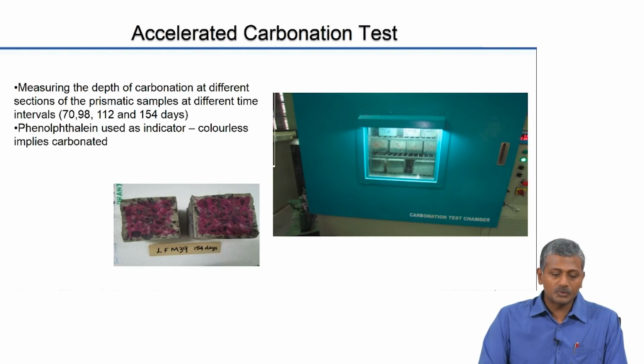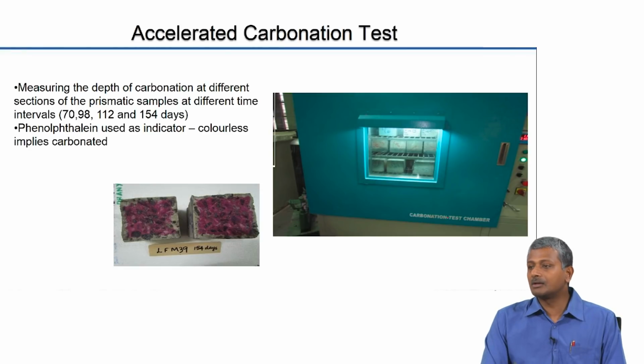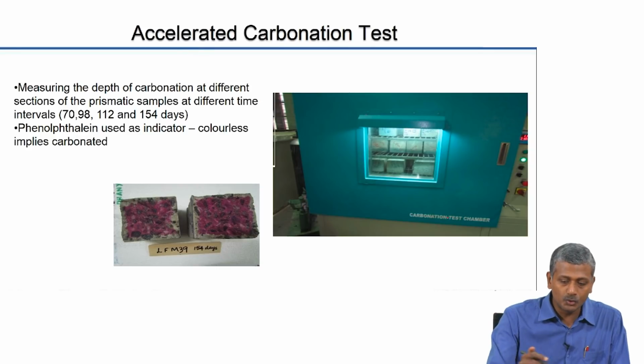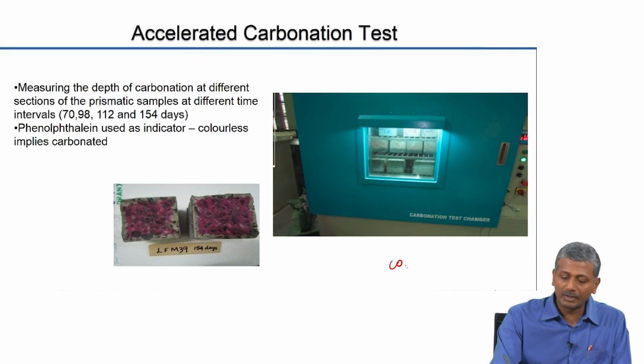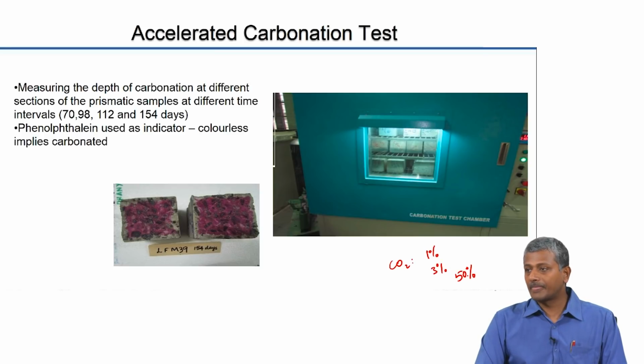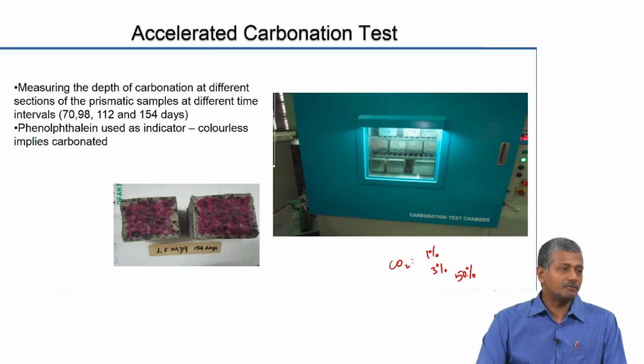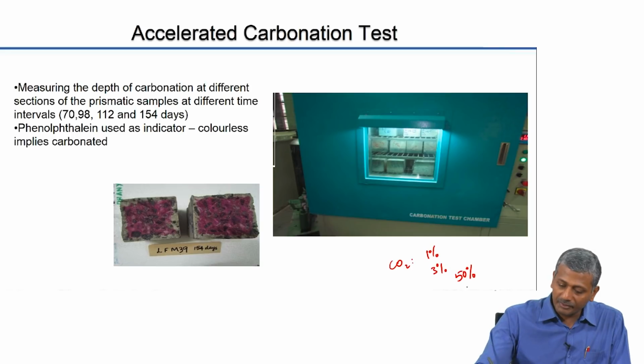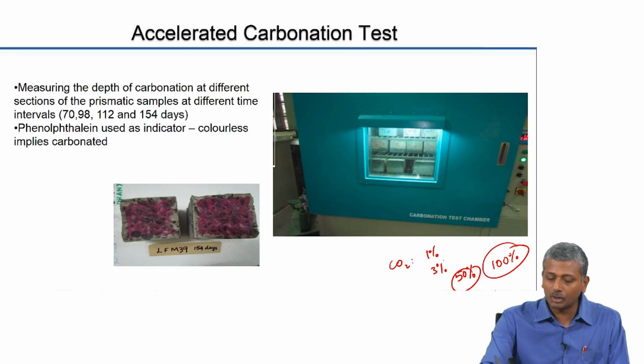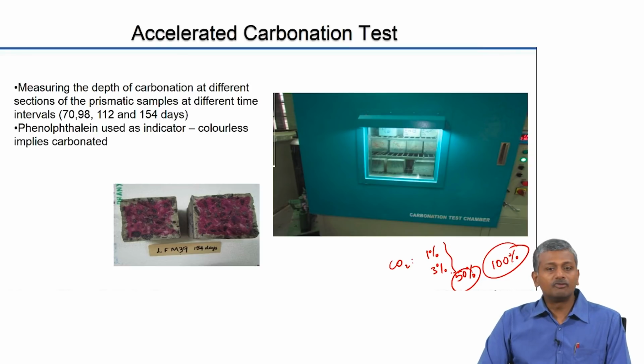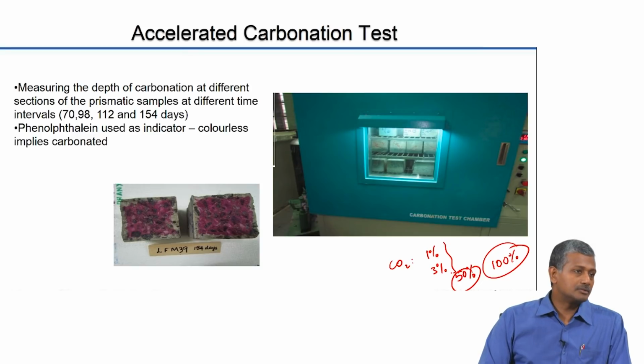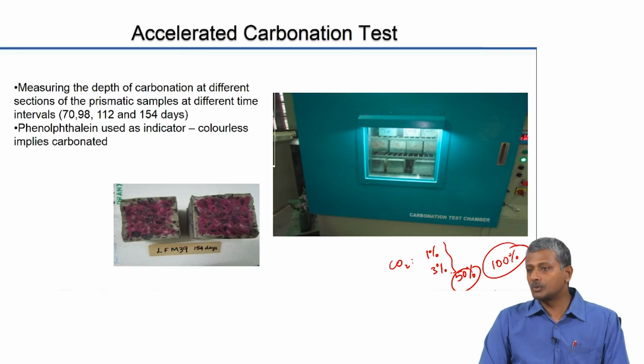Now, for that what we do is we create these chambers where we can control the temperature and the humidity to an extent which maximizes the rate of carbonation. We also choose a high level of CO2. So, CO2 level could be 1%, 3%, or sometimes people have used even 50% inside these chambers. So, we are simulating an accelerated CO2 environment. Of course, this 50% or 100% CO2 is something totally unrealistic. So, most people tend to prefer between 1 and 4% as valid concentrations of CO2 inside the chamber.